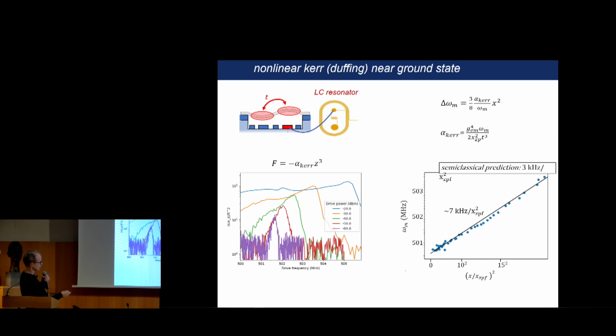And then here what I show you is the mechanical frequency that we observe. So for different forces, for example, here we have the resonance frequency, and then we have the displacement from this axis that I plot here. And you see that it is a signature of nonlinearity. It shows that when we have displacements that are 10 times the zero-point motion, it's highly nonlinear, and it remains nonlinear down to the level of the zero-point motion. What we have also is the slope, and this slope is consistent.